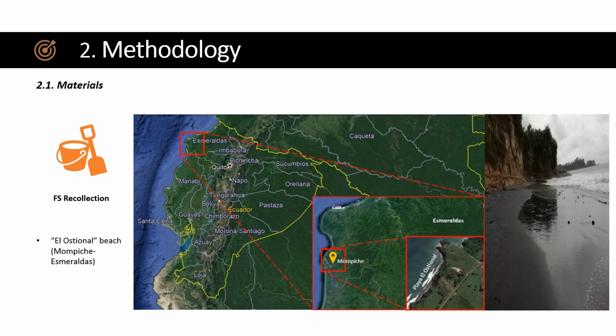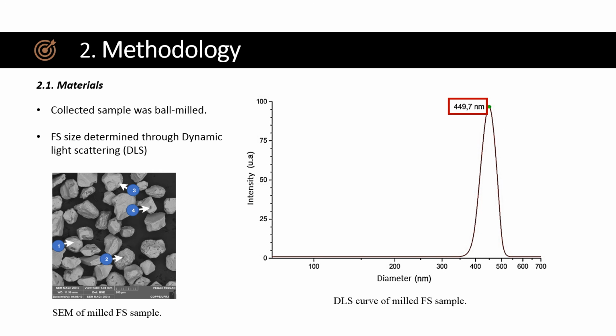For this work, Ecuadorian ferrotitaniferous sands were collected from the El Ostional beach located in Mompiche, Esmeraldas. The collected sample was ball milled using conditions determined in a previous work, and the sand size was determined through dynamic light scattering analysis. As you can see in the SEM image, these sands present an irregular shape, so on average, the particle size is around 450 nanometers.